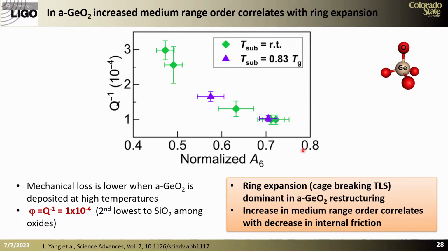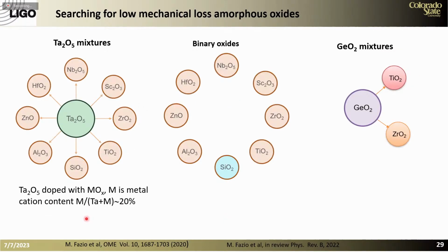So what you see here is that this internal friction is again related to this medium range order. And so glasses that can achieve this ultra stable state are expected to have the lowest mechanical loss. And in fact, that's the reason why in silica we can always obtain a low mechanical loss, because that organization is much more prevalent in silica. Nevertheless, what we measure in germania is a mechanical loss of 1 × 10⁻⁴, which is the second lowest to silica.